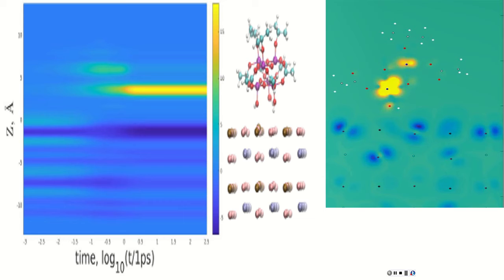Good question, and the answer does exist. The edge of the conduction band originates from titanium, not from oxygen, right? Yes. If you have only titanium dioxide in your simulation cell, your conduction band is composed of titanium 3D and the valence band is composed of oxygen 2P. So if you do projected PDOS, there will be no oxygen-related orbitals in the conduction band.